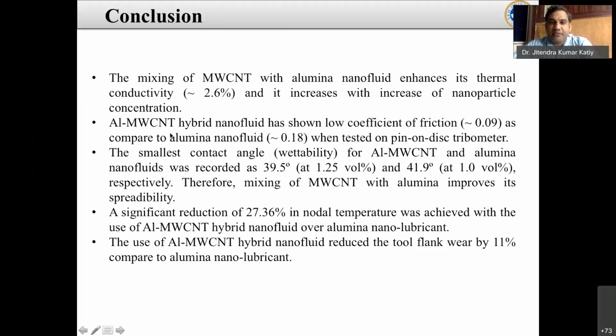So hybrid nanofluid also shows a lower coefficient of friction in comparison to the mono-type nano cutting fluid. We can also get the smallest contact angle. That is also one reason. Through the water contact angle, we can judge wettability and the adhesive property. If the fluid adheres more to the surface, then it can provide better lubricity, like oil. That is the only reason we performed the water contact angle test.